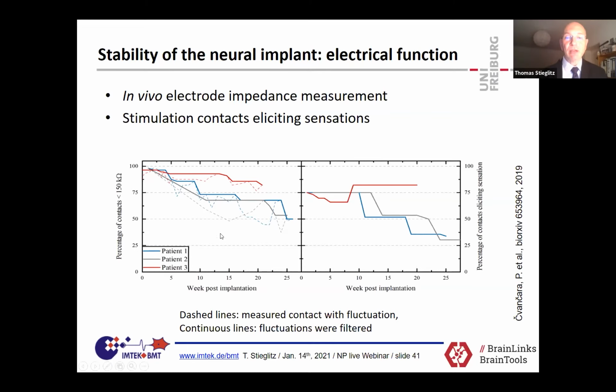And we had here with our upper limb amputees 3 persons, and we checked up first in vivo impedance over time. Have been implanted here up to 25 weeks. And the right-hand side is the contact of eliciting sensation. And that is the important part, because here all those 3 lines go down. I show you on the next slide why these 2 lines with the patients went down. So we were really completely upset because we lost a lot of electrode contacts over the weeks. And of course, some competitors said, that's the thin film part. You know, we told you, that's the thin film. It's much too thin, it doesn't work.